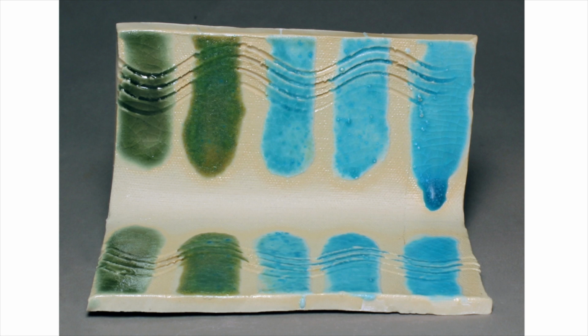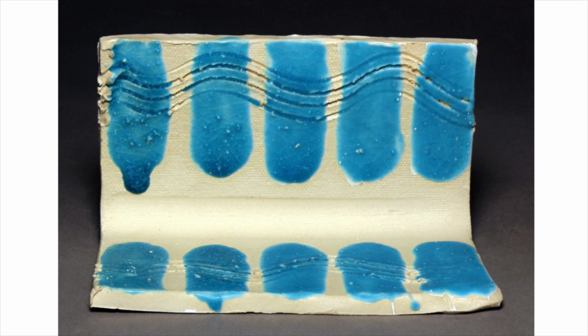Increasing amounts of the flux often lower the melting temperature of the feldspar, which eventually causes it to flow uncontrollably, as shown here in the far right stripe. So more clay is added, like the common ingredient EPK, to that mixture in the last stripe to control the flow of the feldspar and flux mixture. So here, the EPK was added to the last stripe in the previous image in 10% increments.